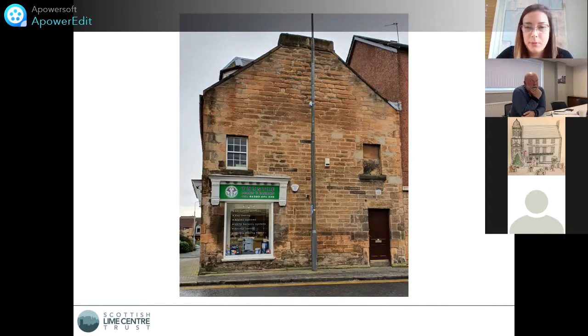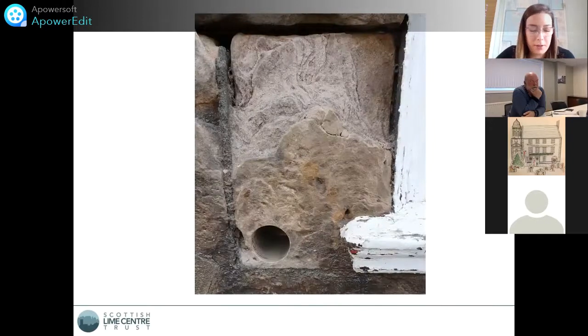As a result, the stone has suffered quite considerably. It has been repointed in cement, which hasn't helped either. And this was our sample location. You can see the stone is quite heavily weathered, and the mortar has actually been completely lost. In this case, maintenance might be actually just checking the stone and then arranging for it to be repointed so that the stone doesn't suffer anymore.